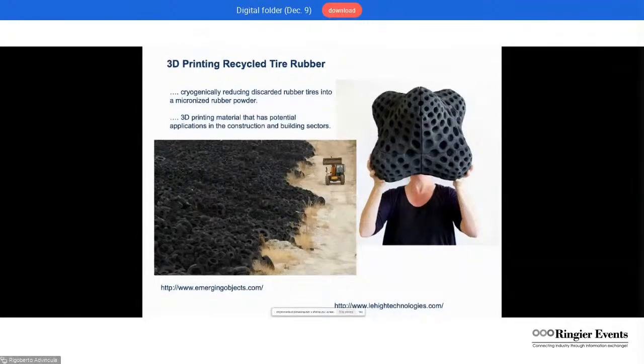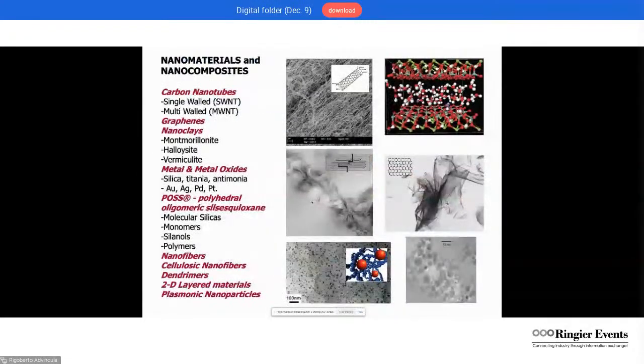So recycling of rubber is possible, except that you need to find better ways or chemistries to utilize them as feedstock sources. Now, the way we've done it in terms of research, and this is really the emphasis of my research activities as a professor, is that we add nanomaterials to polymers or plastics, forming nanocomposites with the percolation theory, allowing us to find the high performance based on composition ratios. So we can use carbon nanotubes, graphene, nanoclay, nanocellulose. A good number of these are commercially available.